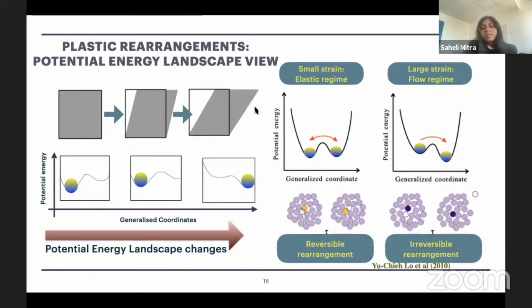But if my deformation is large, at some point one local energy minimum will disappear and the system will be forced to move to a new local energy minimum. And the way the system does so is by locally rearranging the particles. In the elastic regime, these rearrangements are reversible. That means when I remove the load, the system can go back to its initial position. But in the flow regime, these rearrangements are irreversible, and the system cannot go back to its initial state.